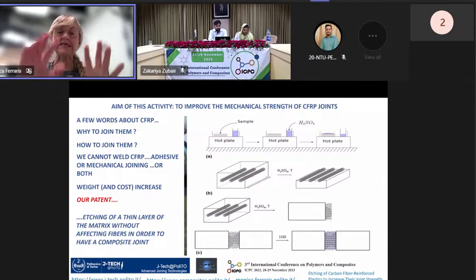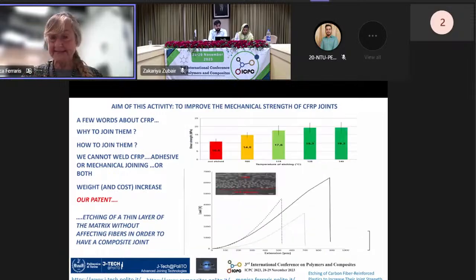This is the aim. This is the lap shear strength of two jointed CFRP samples: non-etched, and then with different kinds of etching. This process is very sensitive to temperature and time of etching, but if it works, you can double the lap shear strength, so you can go quite high in numbers.